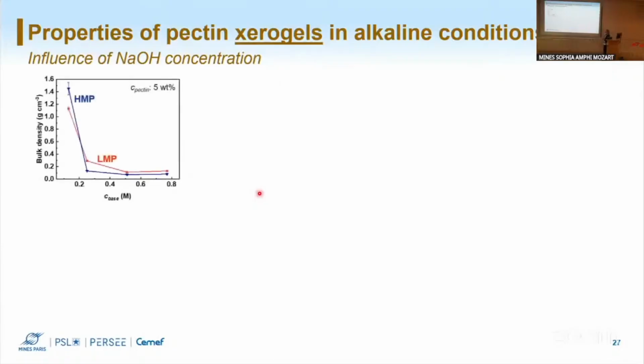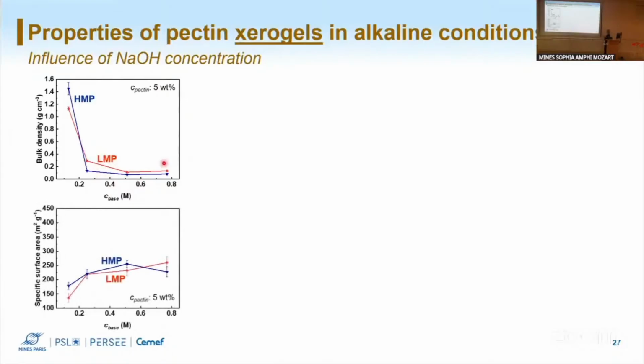Coming to the properties of the xerogel, so dried by evaporation, we see a huge effect on the bulk density, depending on the concentration of base. So again, high and low methoxyl pectin. When the concentration of base is very low, we have very, very high bulk density that is close to the density of pectin. And as we increase the base in our system, we reach values that are very low. Then the specific surface area starts again with lower values, and as we increase the base concentration, they reach values up to 270, 280.